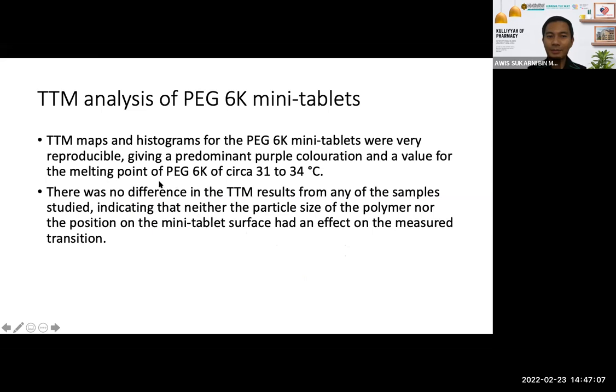The melting point that we get is around 31 to 34 degrees, even though it is lower than the actual value, which for PEG should be around 60 degrees. But there is an explanation for that, which I'm going to tell you later on. And you can see there is no difference in the TTM result compared to the rest of the samples. When we tested on the cap, on the side of the tablet, and with different particle sizes, all of them showed a similar result.